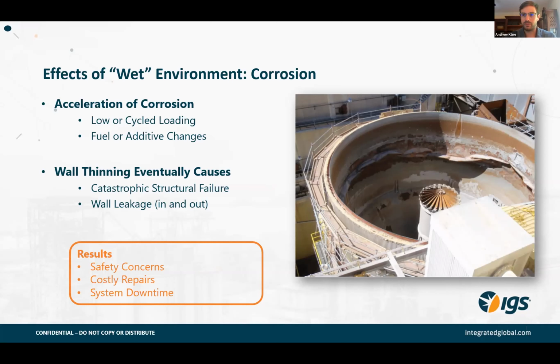But also on the lesser ends, as we're aware that can happen, just wall leakage. When you start to get pinholes and larger holes in the wall, you have air-in leakage, which can cause a host of issues for the mixing of the gases and the efficiencies and the pressure drops through the system. But then also contamination out, which can be a safety issue. And then the cost obviously associated with fixing all that.